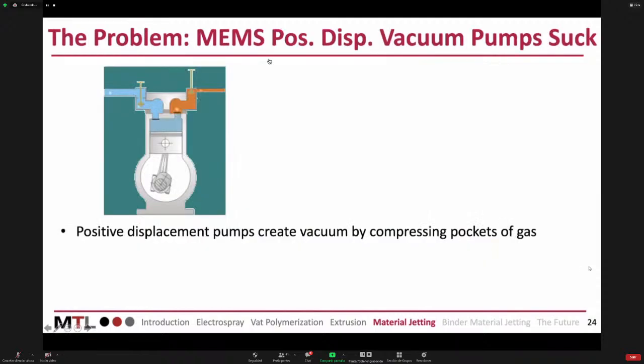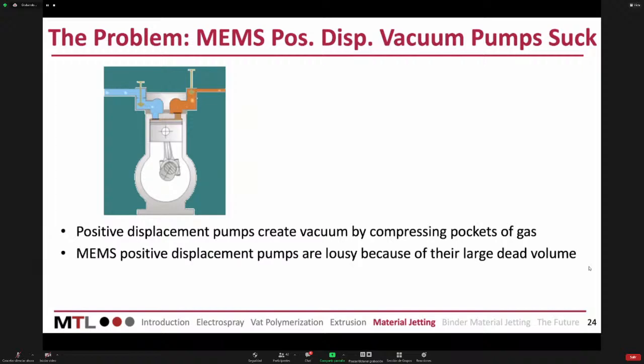And what we did in particular is positive displacement vacuum pumps. So it's a schematic. You see, you cycle pockets of gas from low pressure to high pressure, okay? And this is a standard technology to create vacuum. But the problem is that if you make a microfabricated version, what kills you is the dead volume. So there is not much difference between the maximum volume that I can actuate and the minimum volume that I can actuate. And it's based on that ratio how much vacuum I can make with this technology.